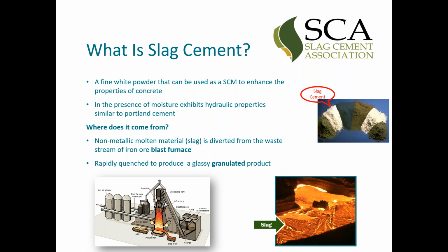The way that it becomes a cement product is that it has to be quenched. It has to be cooled very rapidly so that it can form glass. And then this, of course, is ground down into a fine powder, and you can see a color contrast between, say, Portland cement on the right, slag, and microsilica on the left, and then fly ash, metakaolin, and maybe another fly ash. But it's a very white finished product once it's ground.